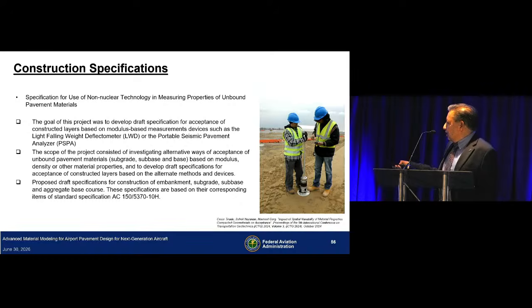And by changing the drop height, you can also capture the stress softening or stress hardening behavior of these materials in the field. And we worked with the University of Texas at El Paso, and Dr. Sohail Nazarian was the principal investigator on this particular project. And there is a report. That report has not been published yet, but the results of the study are published in a paper that you can access. The paper was published in the International Conference on Transportation Geotechnics.